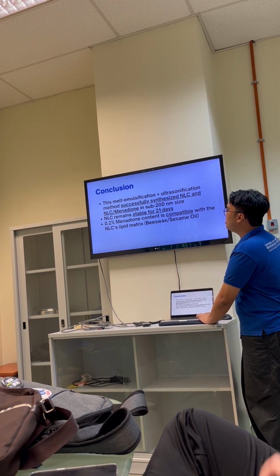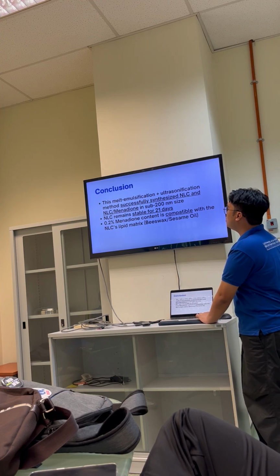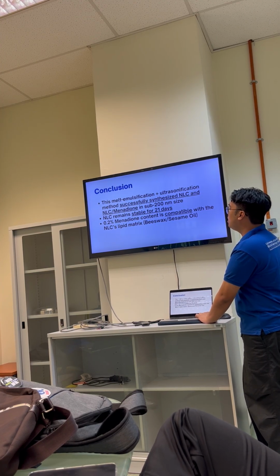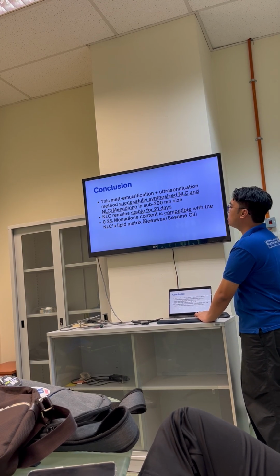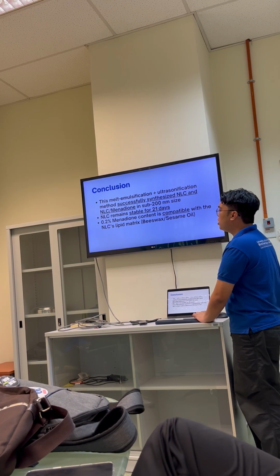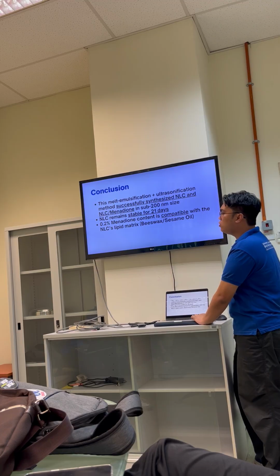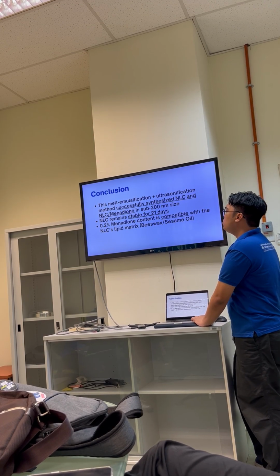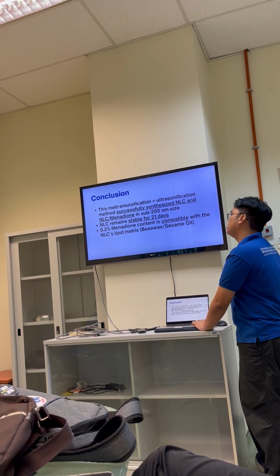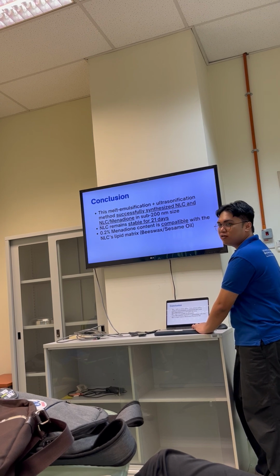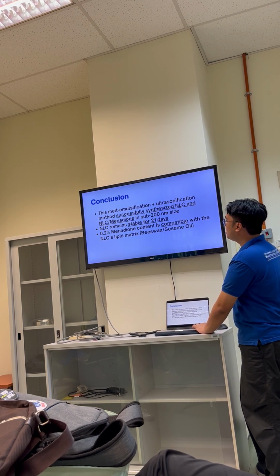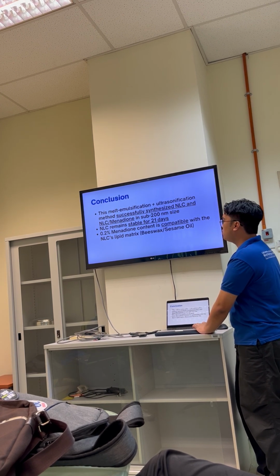So the conclusion would be this melt emulsification and ultrasonification method successfully synthesized the nanoparticles that we need, in sub 200 nanometers of size. And the NLC remains stable for at least 21 days. The 0.2 menadione content of drug is compatible with the lipid matrix that we have chosen, which is beeswax and sesame oil components.